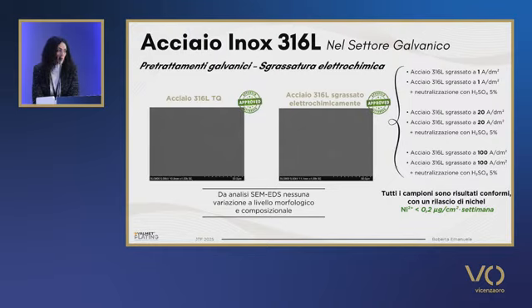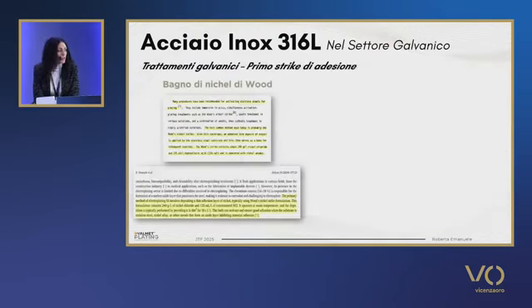But irrespective of the current being used, none of these samples yielded or released any nickel. As a matter of fact, there are no morphological, no composition variations after the test. So we may clearly say that the polishing, the degreasing process does not lead to any release. In the case of oxygen getting in touch, something might happen.